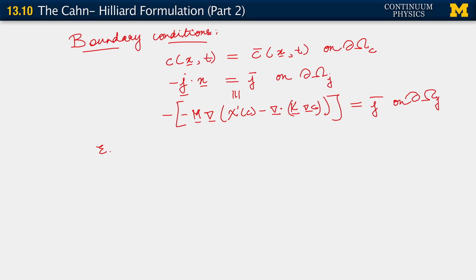We saw that the variational formulation in order to have equilibrium gives us an additional condition on the boundary. So we can have an additional boundary condition, which we may call an equilibrium boundary condition. Comes out of the variational arguments. And it says that if you want the system to evolve towards equilibrium, at equilibrium, you also need another condition, which turned out to be k grad c, the whole dotted with n equals 0 on all of the boundary.